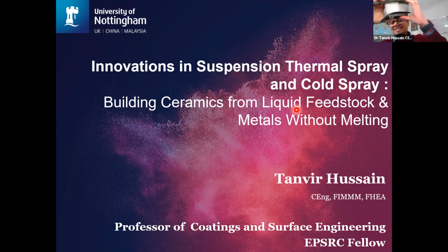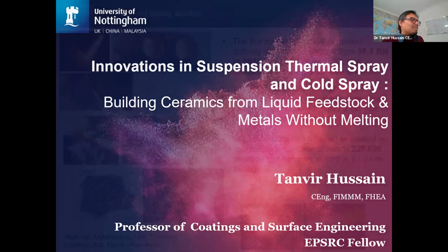That's from an aero engine component, a nozzle guide vane. You can see that discoloration because it had quite a few hours of service. Similar sort of systems. I also have another nice and shiny one, which is titanium nitride. This is an erosion protection coating on top of a compressor blade. So let's make a start then.